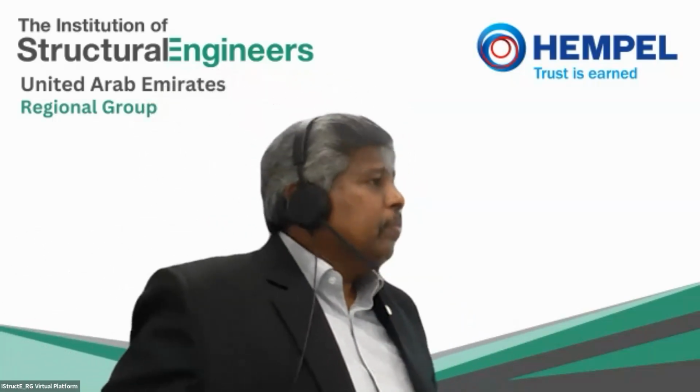I also mentioned it is ISO 9223, but that is a theoretical calculation that you can do. But you can also do, at the same time, a practical measurement, and you can calculate the metal loss from that as well. So there are two methodologies that people use, because we were recently working on one of the projects in Saudi Arabia where we offered them the theoretical. They also wanted a practical measurement where they said, can you come and place some coupons? Because almost every consultant says this is only C5. And then we told them it is C4. And the cost between C5 and C4 is quite substantial.